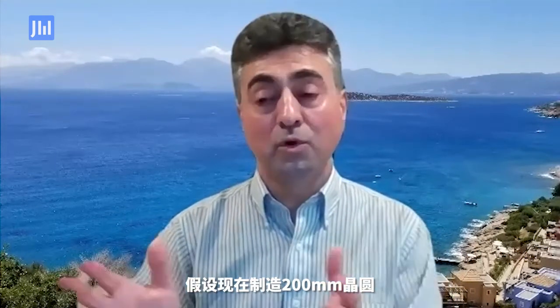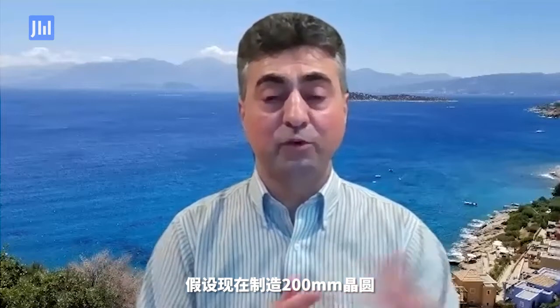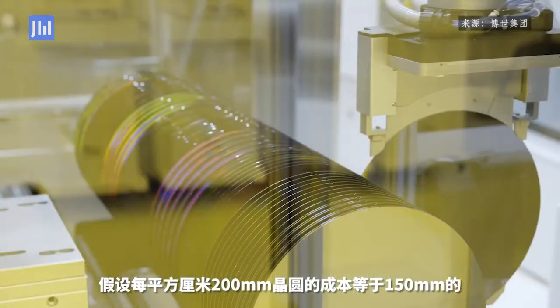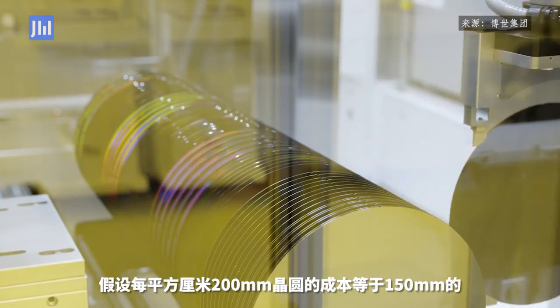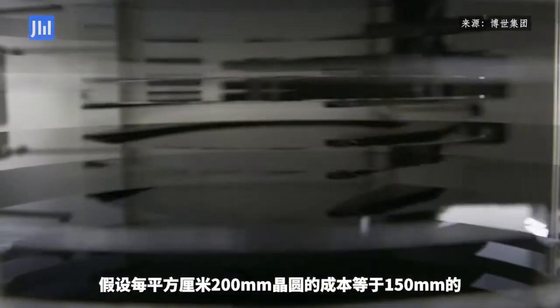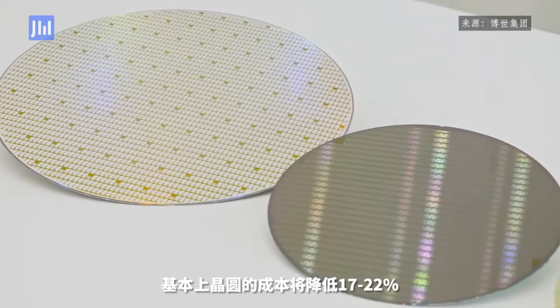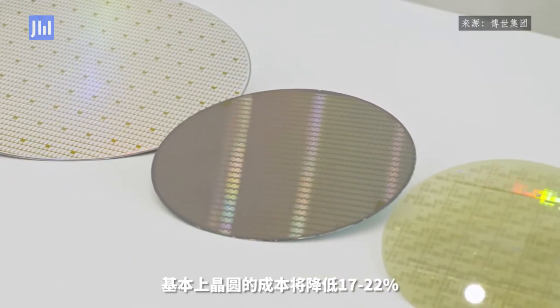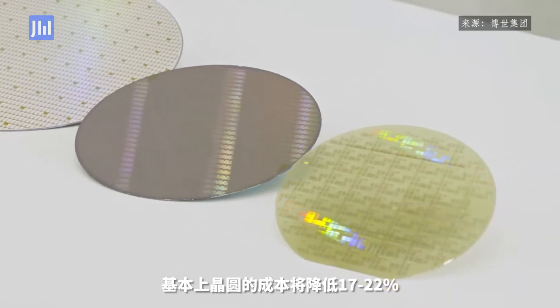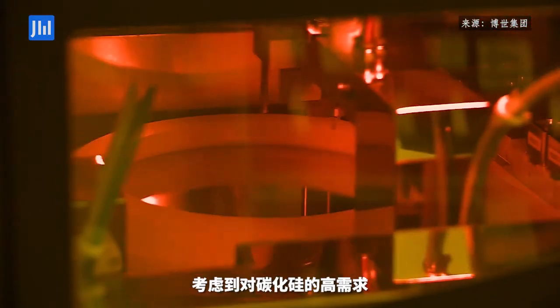However, you need to pay more for the wafer itself. So assuming you go to a 200mm wafer, you get 45% more material. And assuming that your cost for the 200mm wafer per centimeter square is the same as the 150mm wafer, depending on your specific numbers, it will bring you anywhere between 17 to 22% in cost reduction for the device. Given the high demand of silicon carbide, it's definitely the way to go.